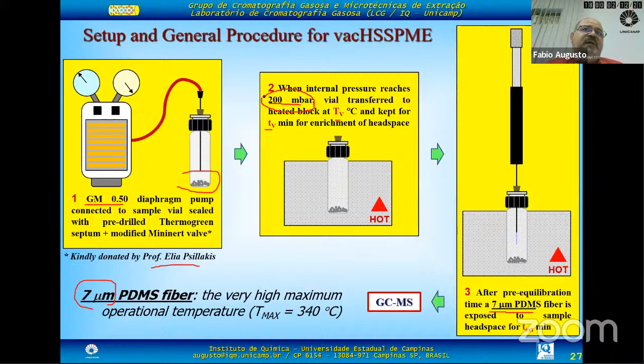We are trying to obtain a better pump, but the problem is that if you try to apply less pressure here, this interface would not stand such a very low pressure. But 200 millibars is 0.2 atmospheres. It's low enough to result in a very, very pronounced acceleration of the mass transfer process.